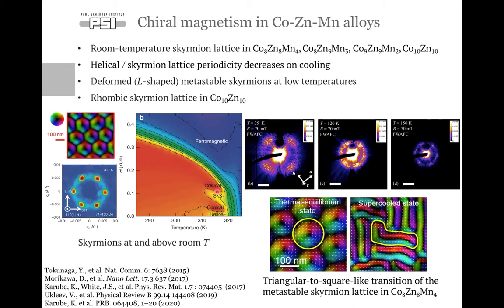the helical and skyrmion lattice periodicity just below TC is about 150 nanometers. But as you cool down to cryogenic temperatures, to helium temperatures, 20 K or so, the helimagnetic pitch gets as short as 70 nanometers. So there is a factor of 2 decrease in the periodicity of the magnetic spiral and skyrmion lattice. Also, interestingly, this transition is accompanied by a change in the lattice shape for magnetic skyrmions.